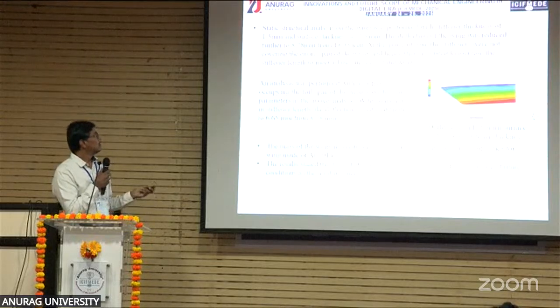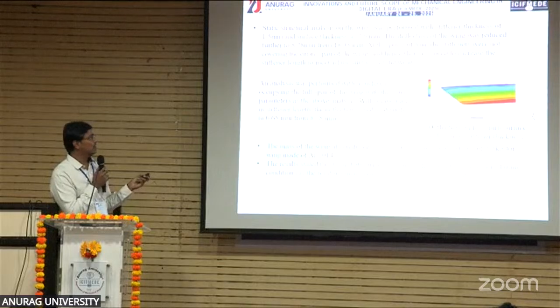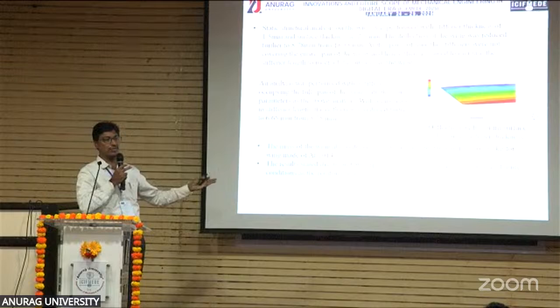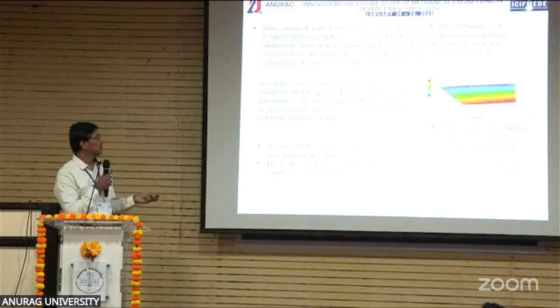Further, they created 4 separate entities: the stiffeners, top and bottom surfaces, and the root thickness for the longer side and the shorter side of the wings, and processed it. With this static structural analysis, the deformation was reduced from 18.33 to 8.78 millimeter. Further, they performed ANSYS again with a stiffener occupying the full span. Initially the stiffeners were not applied for the full span of the wing, so they did it with the full span.